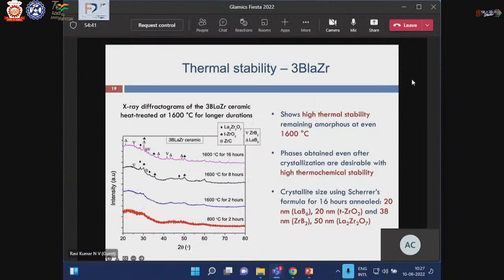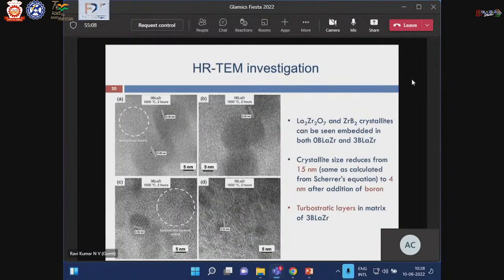Maybe if we heat treat it at that temperature for around 15 or 16 hours, you can start seeing very small crystalline phases of borides of zirconium, lanthanum hexaboride and so on, which are relevant for high temperature applications. So we have already been able to make such materials, which are quite stable, and the challenge was basically to make them into a coating formulation. These are high resolution transmission electron micrographs showing how they are embedded in the matrix, and how we make sure that these crystalline phases do not grow and grain growth is inhibited because of the surrounding constraining matrix.